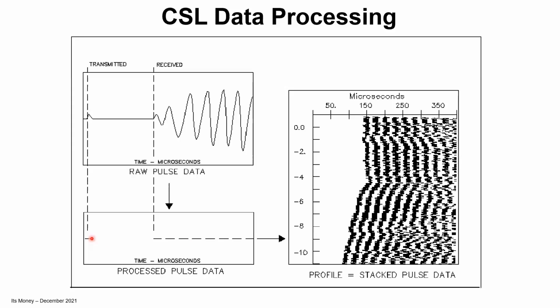The easiest way to do it, or my preferred way anyway, is to do a rectification on the signal where each positive peak is printed as a dash, each negative peak is a gap. So this dot dash line gives us all of the timing information and some of the amplitude information out of the raw curve. The lines of data are stacked consecutively as we come up the shaft. And so we build up this vertical profile of the transmission time through the concrete.